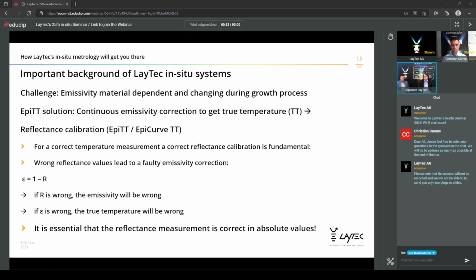This is very fundamental to get the correct temperature value, which means, on the other hand, if you do it in the wrong way, or it's not done properly, you will have a faulty emissivity correction, since the emissivity is 1 minus R, so 1 minus reflectance, so it has a direct impact on the emissivity correction. If R is wrong, the emissivity will directly be wrong. If the emissivity is wrong, the temperature will be wrong. So finally, the reflectance measurement is the backbone to get the true, or what we call true temperature, the absolute temperature value on the wafer.